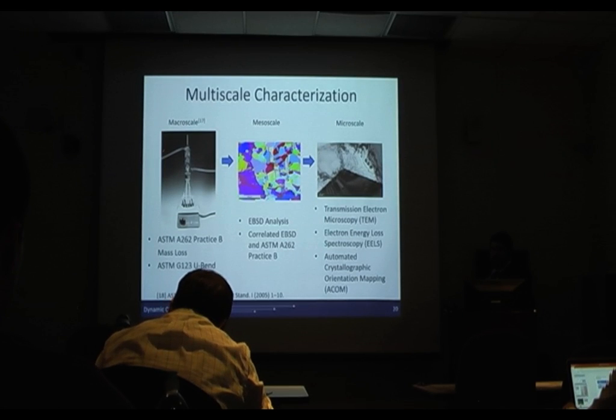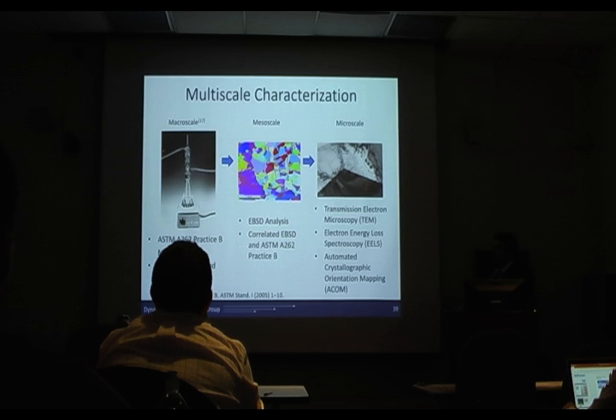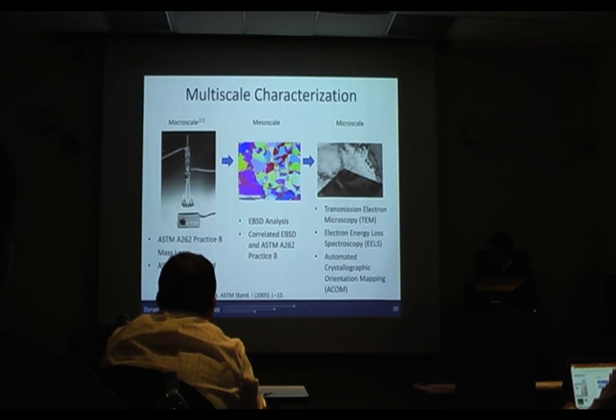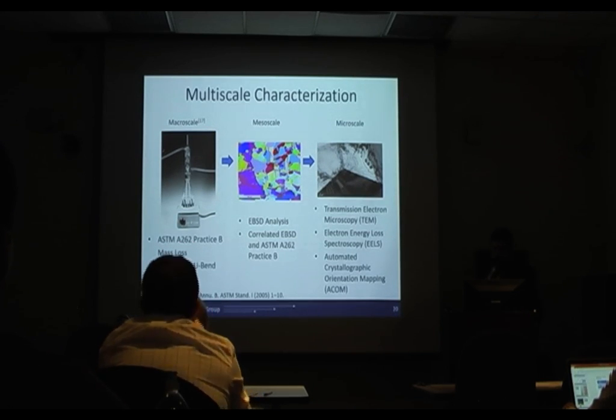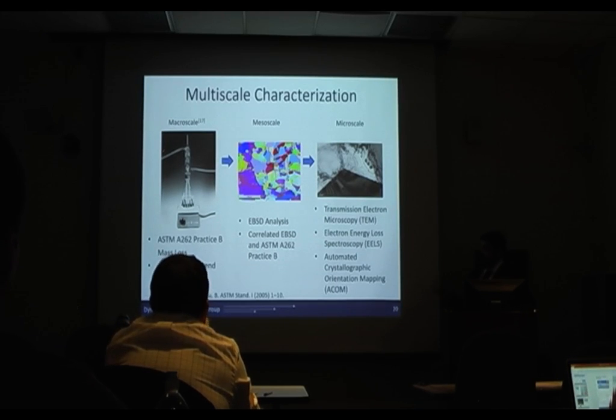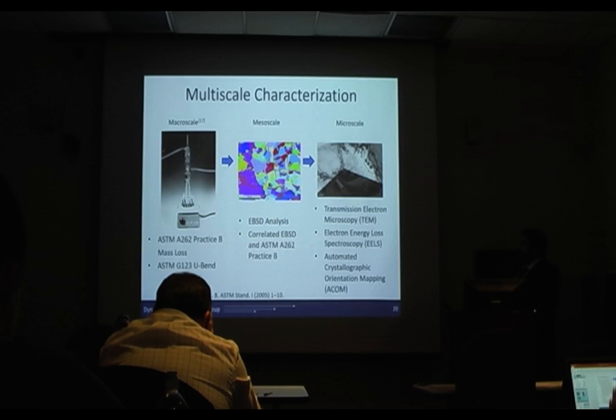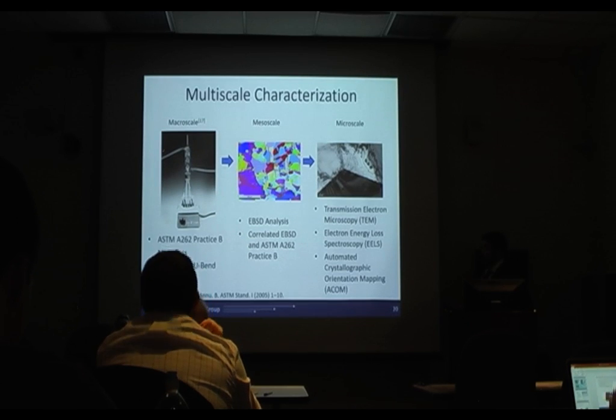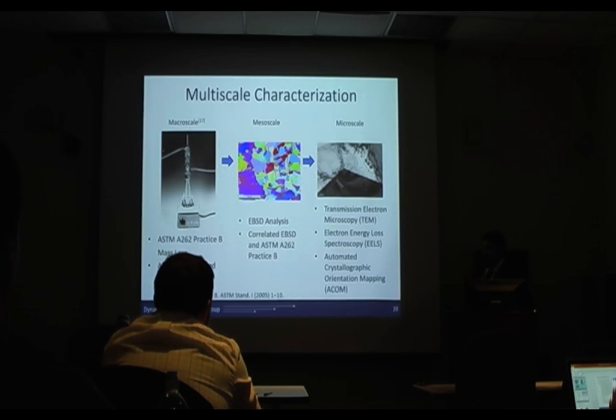I used a multi-scale approach, starting on the macro scale using ASTM corrosion techniques, primarily the A262 practice B mass loss for the intergranular corrosion and the G123 for U-bend for the intergranular stress corrosion cracking. At the mesoscale, I used primarily EBSD analysis and also correlated EBSD and corrosion. And then on the microscale, I used transmission electron microscopy and electron energy loss spectroscopy coupled with that, as well as automated crystallographic orientation mapping, which I'll be referring to as ACOM.